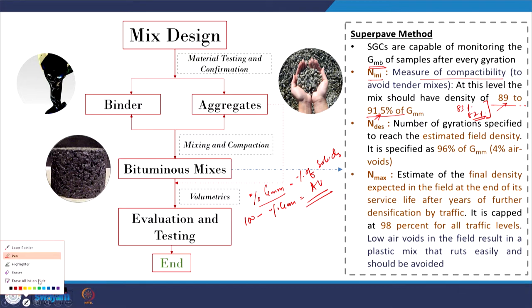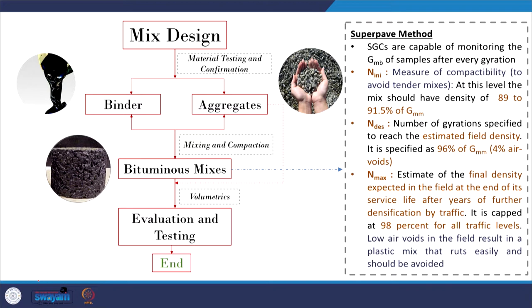If after N-initial the air void is very high — say 83 or 82 percent of GMM — the mix will be very difficult to compact in the field. N-initial helps reject mixes that are too difficult to compact or too tender in nature, making it an important criteria in Superpave mix design.